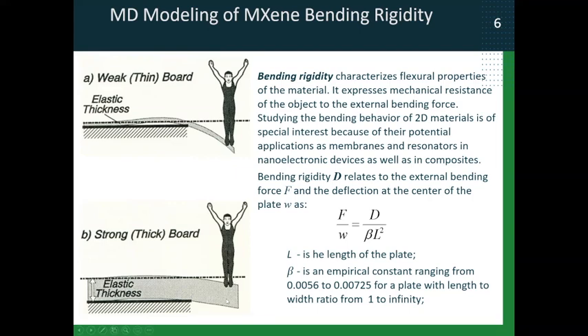So this is bending rigidity in simple words. If you want a way to calculate it, here is the equation which allows you to calculate it. So D is bending rigidity here. And if you know the force F and displacement W, and also the length of your plate, so again, you model your MXene monolayer as a plate, you can calculate D bending rigidity using this equation.